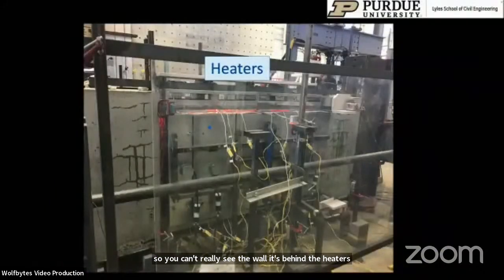And this is a photograph of the experiment in operation. You can see the red hot portions that are the heaters heating up the wall specimens. It's almost red hot behind the heaters. You're also seeing some moisture coming out from the concrete as well.